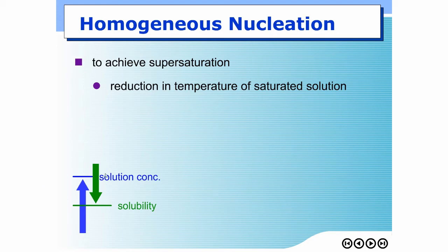When you decrease the temperature, solubility decreases, and for the brief moment before precipitation takes place, this gap is called supersaturation, because the current concentration in the solution exceeds solubility. Of course, when you leave the solution for a while, precipitation takes place, reducing the concentration in the solution to be equal to solubility, and the solution becomes what we call a saturated solution. Okay?